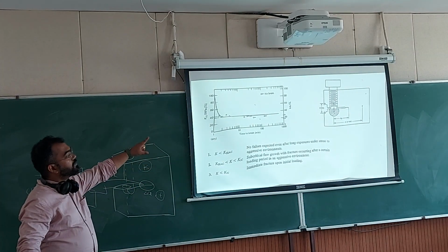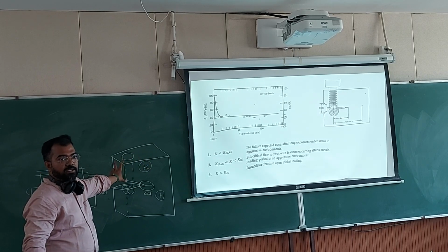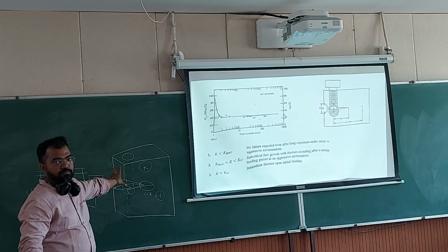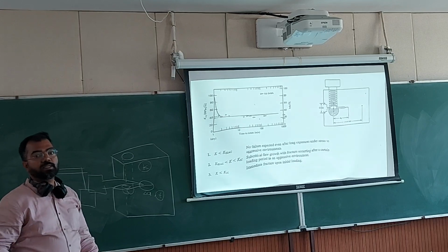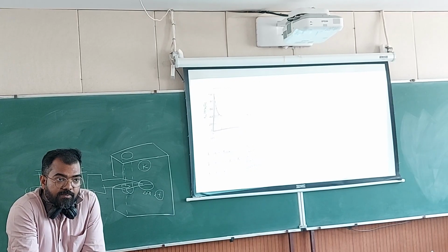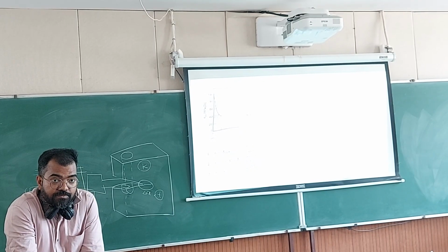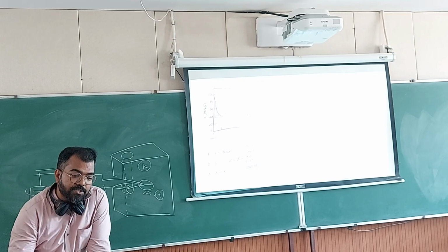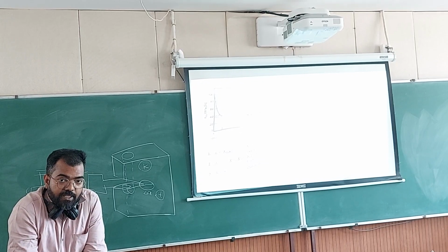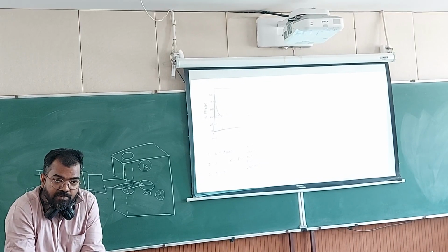Okay. So for this specimen, they propose that even if you don't have a fatigue pre-crack, it is okay. So EDM we can use. The EDM will also not generate that fine a crack. Yes, that's not fine, but we can use it for a test. For polymers, you can do it easily, but polymers will have other problems. For polymers, when fracture testing is done, there is no fatigue pre-cracking. You just create a sharp crack with a blade. That you cannot do in metal. And the blade is also not that sharp. Okay. But for polymer it works.